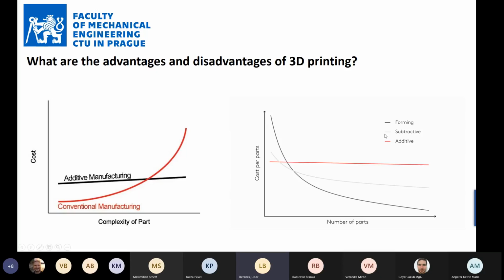On the other hand, when you use basically machining, you can use different technologies of machining, which are quite cheaper than the additive manufacturing. Or if you really want to go for mass production, today basically the whole automotive industry, whether it's plastic, whether it's metal, you use injection molding or high pressure die casting. So you use technologies which are quite expensive when you develop them, when you build these technologies for specific parts, because you have molds which you have to make that are quite expensive, you have some production equipment, but then the production times are on the level of seconds.